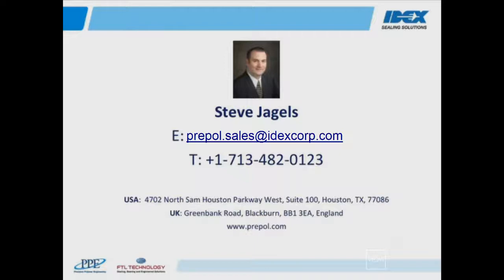What would be the H2S test conditions? Yeah, I think this may be referring to the presentation. What we tested was 25% H2S in the NORSOK protocol, and we've tested 25% H2S up to 175 degrees C. What is the hardness of the low temperature FFKM material you mentioned? We have several versions available depending on the application. The particular grade we tested, and that is shown in the data, is a 90 Shore A material designed for high pressure oil and gas applications.